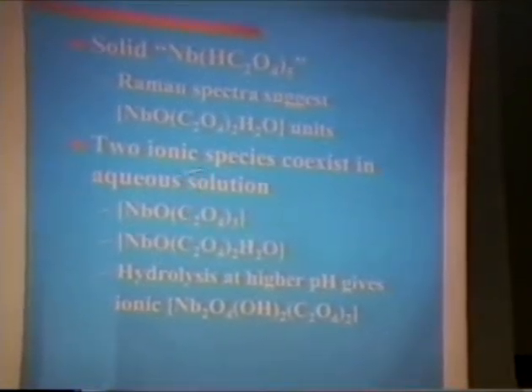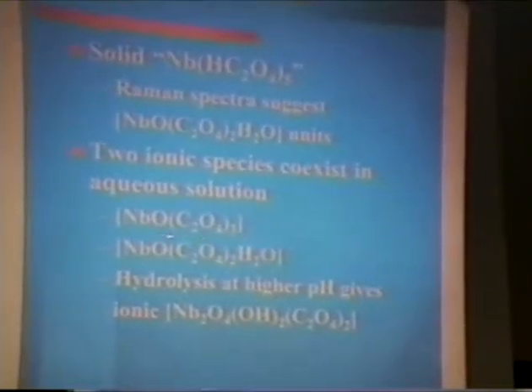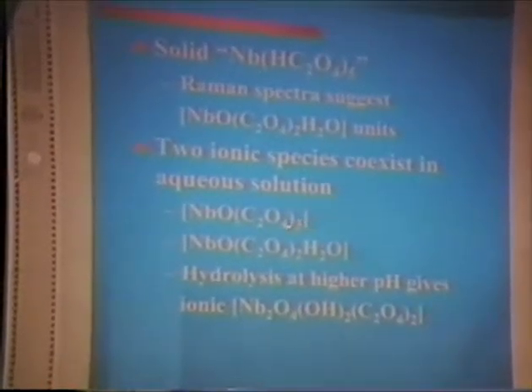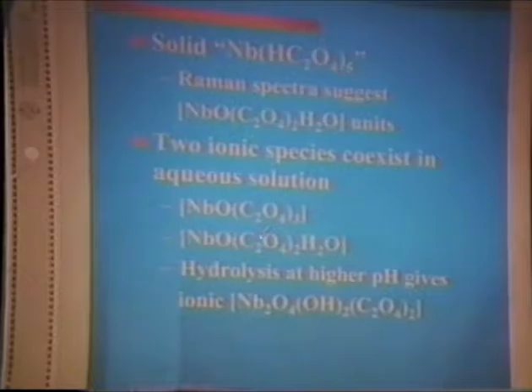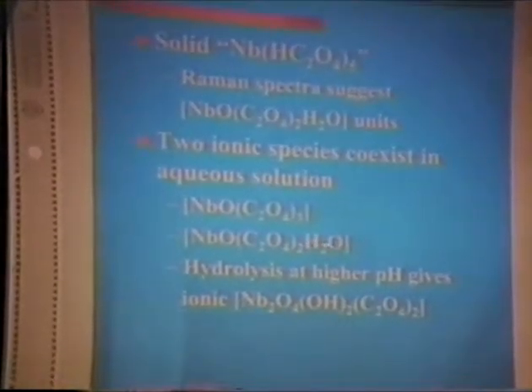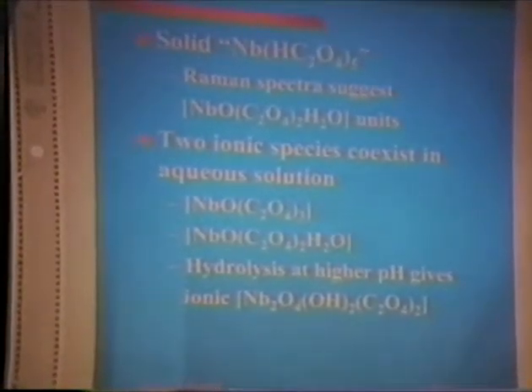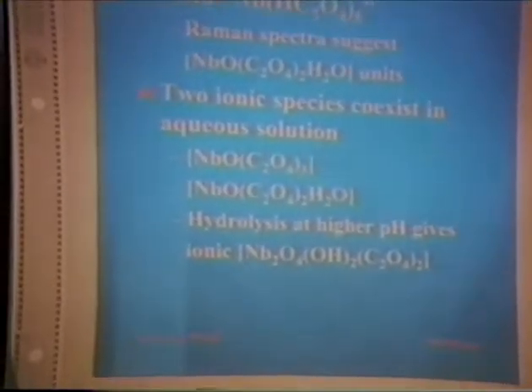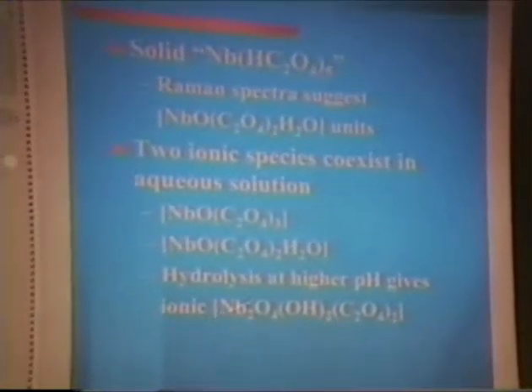Wax sees two ionic species in aqueous solution. One is this complex with three oxalate units. The other one is two with some water here. And the thing that occurs is that as the pH goes up, and we're talking about a pH of three, you begin to see some hydrolysis, and you begin to get some dimerization.